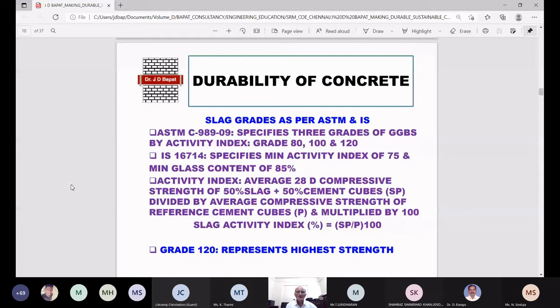Again, when you come to IS, this is a very recent standard. Earlier it was not there. IS 16714 specifies minimum activity index of 75 and minimum glass content of 85%. So you can see the difference. In ASTM standard, glass content is not specified, but activity indexes are specified as 80, 100 and 120. Whereas as per Indian standard, that 75 is actually the activity index. So there is some similarity between ASTM and IS standard over here.